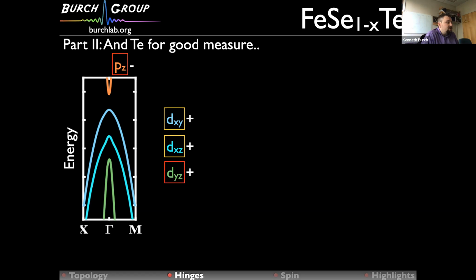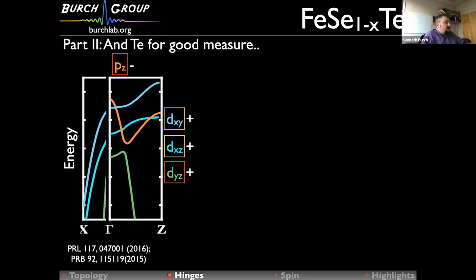So the point was, if you instead of looking in the plane, if you turn your attention out of the plane, then you can have a scenario where as you tune from, say, iron selenide to iron telluride, you can increase the bandwidth of this pz orbital and also change the splittings with spin orbit coupling. And long story short, along the z direction, you can have this pz orbital come down and cross the first 2 without mixing, creating bulk Dirac points, essentially because they're of the wrong representation, they can't mix. But with the third dyz orbital, it can. And so you can get this inverted band gap, which is exactly what you would want for a normal topological insulator. So this would suggest you would have a topological insulator with topological surface states.